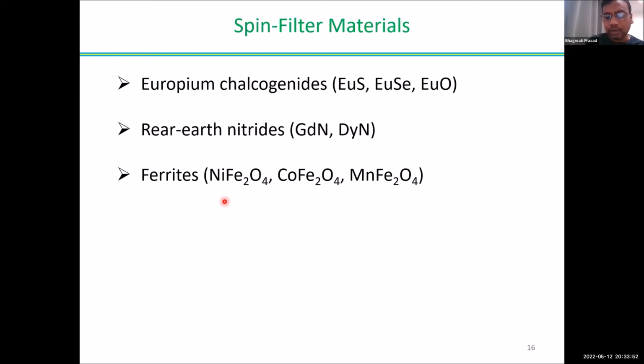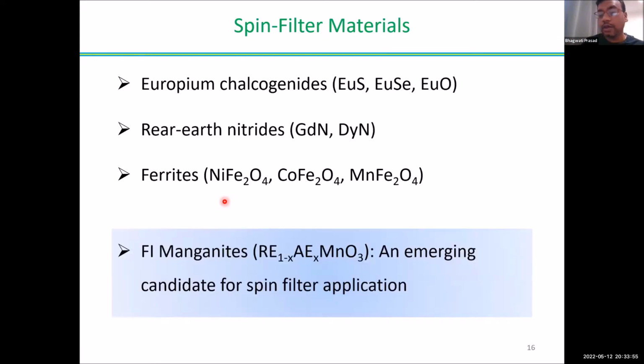Okay, so what about ferromagnetic insulating manganites? Because the manganites have similar structures, they are perovskites, and there are a lot of perovskite systems that are conducting in nature. So you have conducting perovskite electrodes, on top of which you can put them, and they are a simpler system to grow compared to ferrites. You don't need to worry about any damaging of the films when you expose those films to air. So it's quite a robust system.